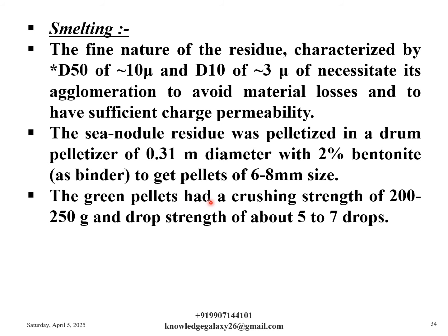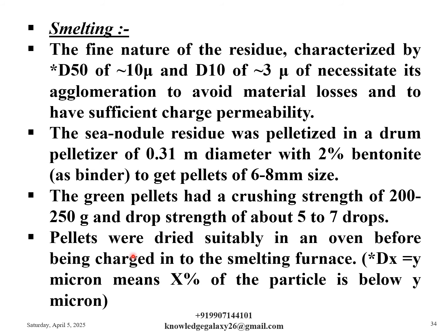The green pellets had a crushing strength of 200 to 250 gram and drop strength of about 5 to 7 drops. Pellets were dried suitably in an oven before being charged into the smelting furnace. Here Dx equal to y micron means x% of the particles are below y micron.